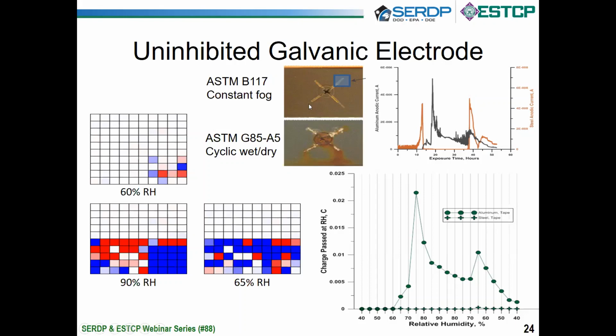So again, if you look at a B117, which is a continuous film of water, electrolyte on the surface, that's part of the reason you do not see this happening. If you drop down in the relative humidity again, so we've cycled up and now we're cycling back down, you can see that electrolyte layer break up and you can start seeing that aluminum corrodes again.